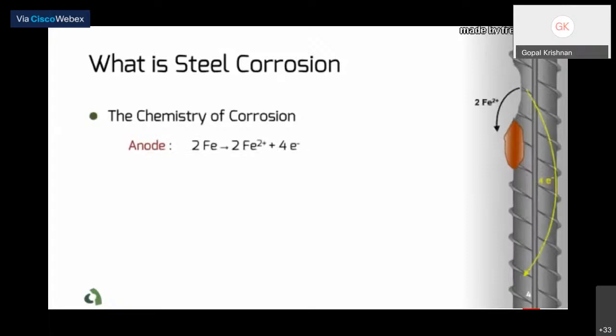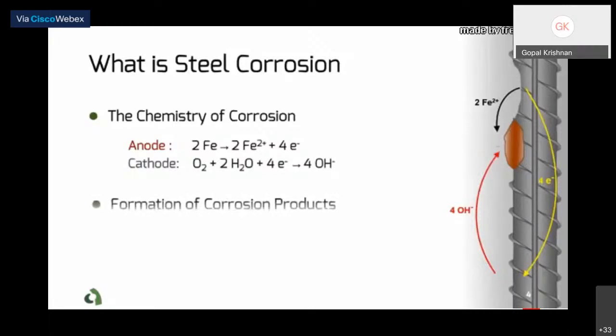On the other hand, another portion of the reinforcing mesh acts as a cathode. In the cathode, oxygen combines with water and the electrons to release hydroxide ions. This shows that the reactions require both water and oxygen to occur. The volume of corrosion products, especially Fe2O3, is significantly higher than the original steel. This will increase the internal pressure and consequently crack the concrete.